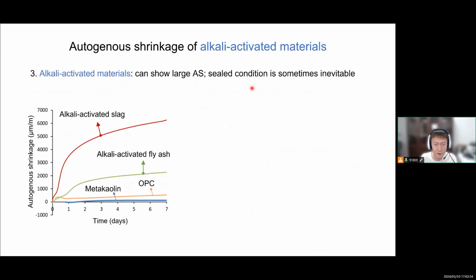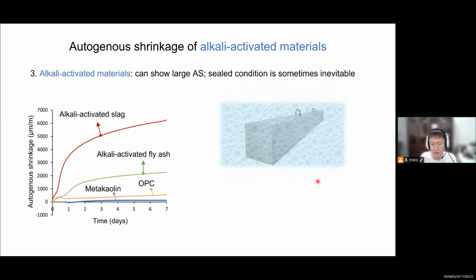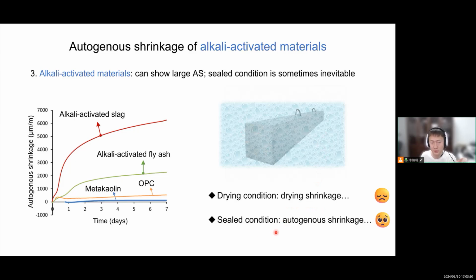It is also because the sealed condition is sometimes inevitable, for example, for concrete with a certain thickness. Even though we apply some moisture or water, for example, a submerged condition of the sample, the water may not readily penetrate the inside to cure or compensate the self-desiccation everywhere because the concrete is large. And even though we put it in the submerged condition, it has its own problem. We think, okay, drying condition is not good because there's drying shrinkage. Sealed condition maybe not good because there's autogenous shrinkage again. Then how about we use the submerged condition? Actually, it has its own problem and may not be optimal.